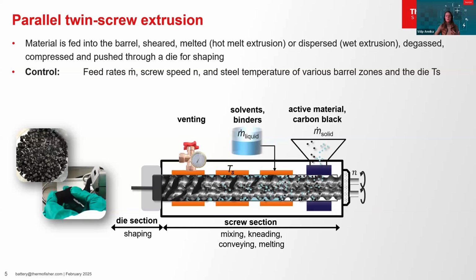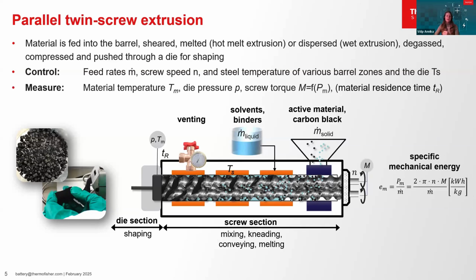The parameters to be controlled include material feed rates, screw speed, and the temperatures of the various barrel zones and the die. These settings influence the measurable parameters such as the material temperature and the pressure in the die, as well as the screw torque and the material residence time. An important process parameter is the specific mechanical energy input, or SME, which is calculated from the power required for the mixing or the torque that applies to the screws. With a die attached, the material can be formed into pellets or sheets if its viscosity allows. This applies for semi-dry electrode processing, but most often electrode slurries are required. For mixing those, no die is needed, as presented on the following slide.